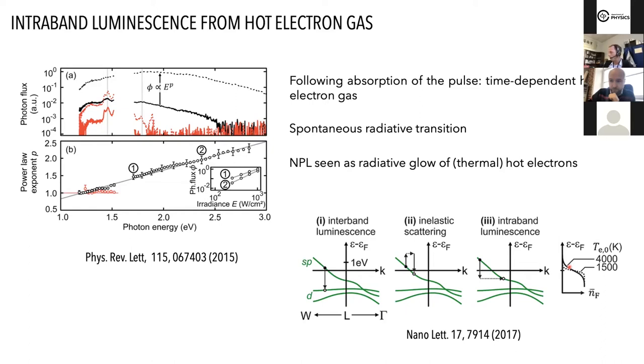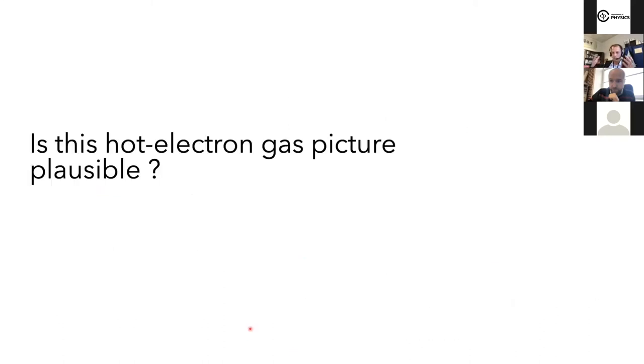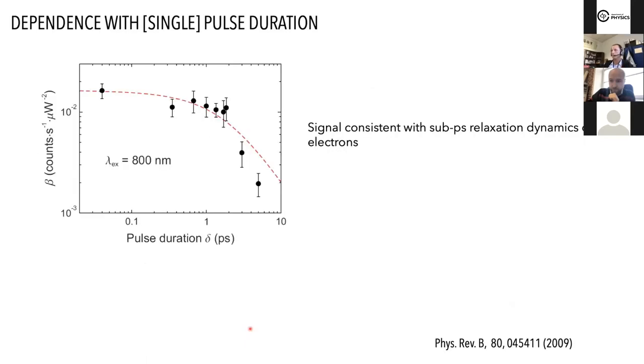Okay, so is this hot electron gas explanation plausible with the rest of the experiments that have been published here and there? Well, and this is going back to one of the questions that was raised, what is a typical lifetime of this effect? Well, this is a 2009 paper from my colleagues in Milano, where they were looking at the efficiency of the process as a function of pulse duration. And you can see that as you increase the pulse duration, the efficiency drops down and saturates whenever the pulse duration is around 1 picosecond.